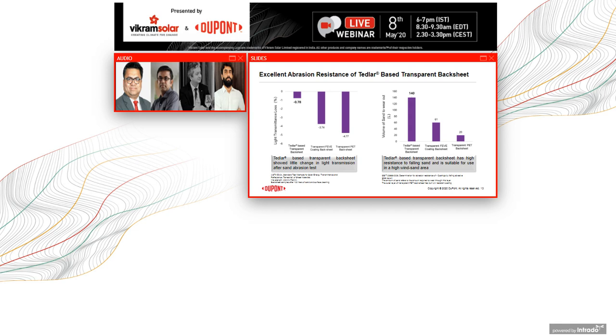So what we see here is a Tedlar-based transparent backsheet on the left. We are measuring the light transmittance, and it only loses a fraction of a percent of light after the entire test, which is way over the lifetime of the module. Compared to some other competitive materials, you can clearly see the difference, both in terms of the loss in light transmittance, and on the right here, an equivalent test which shows how much sand is needed to actually wear out the backsheet, which is significantly more than any other competitive backsheets, and also significantly more than anything that a backsheet would see in actual field deployment.